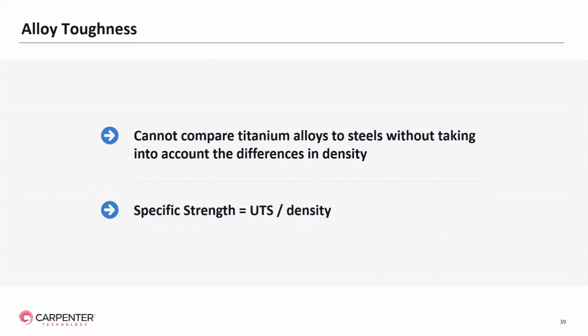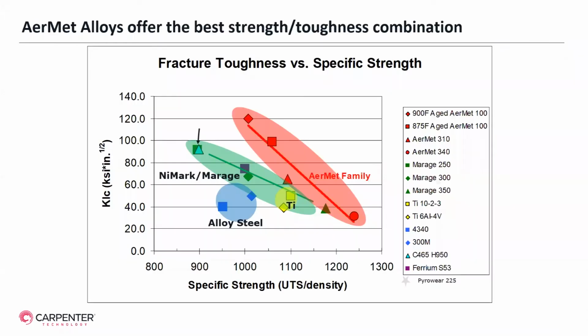Now, when we talk about toughness, you can't compare the titanium alloys to steels without taking into account the differences in density. Specific strength is UTS divided by density. So if we put those on the next graph, you can see where specific strength versus toughness, the AirMet family far exceeds all the other alloys that we've been discussing. Likewise, when you talk about damage tolerance, which is very critical in all the applications that are needed for aerospace and defense, AirMet once again exceeds most of the other alloys.